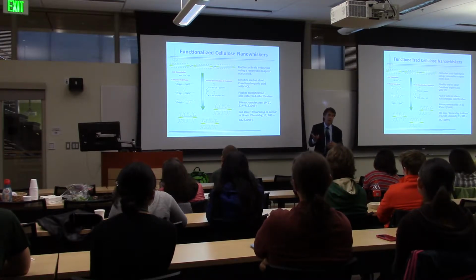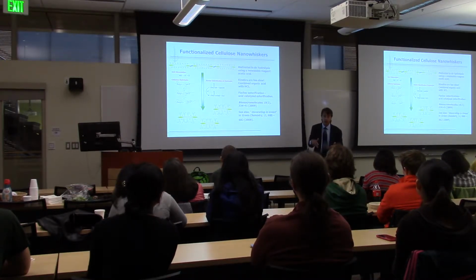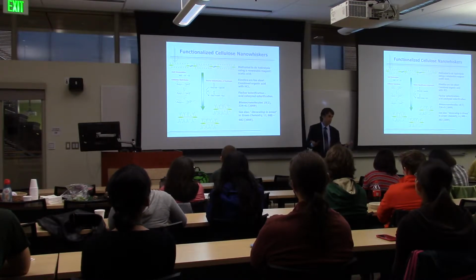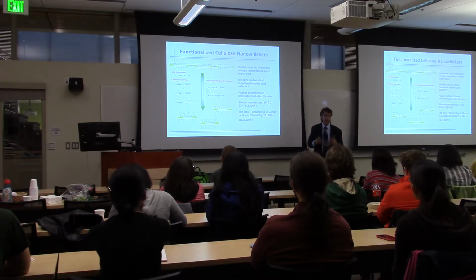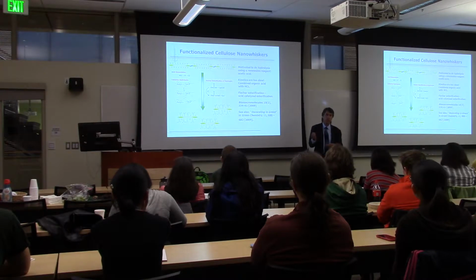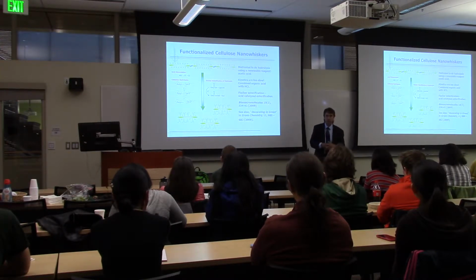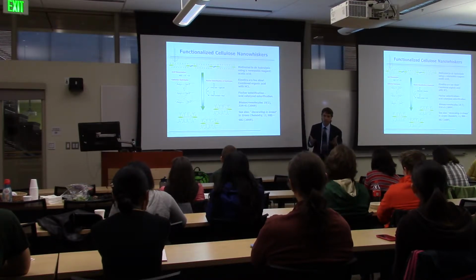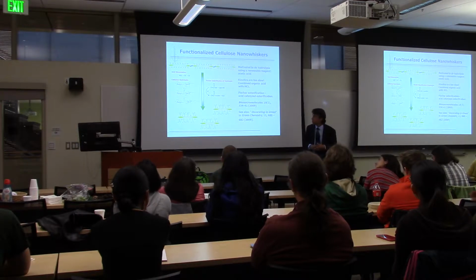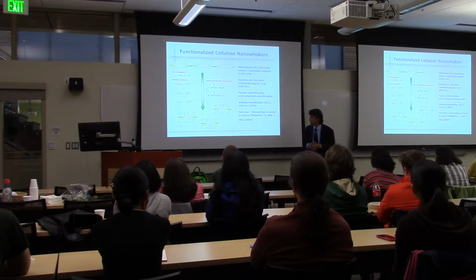So we started making the whiskers instead with hydrochloric acid, and then at least it didn't turn black, but when we did the polymerization, we just got like a powder. And if you do polymer synthesis at all, when you have just powdery stuff, that it's very low molecular weight. And so as we looked at those materials, they had terrible properties. And so we really had to come up with a better way of making the cellulosic nanowhiskers.